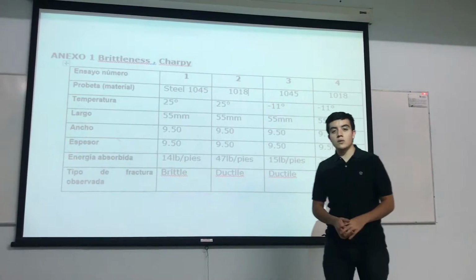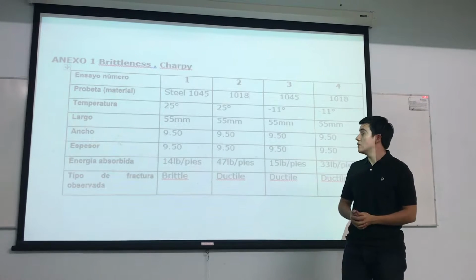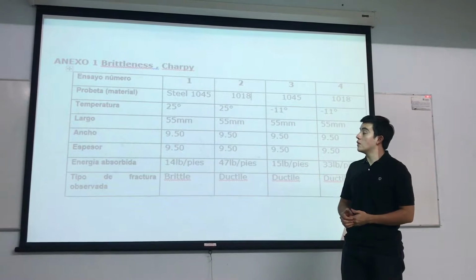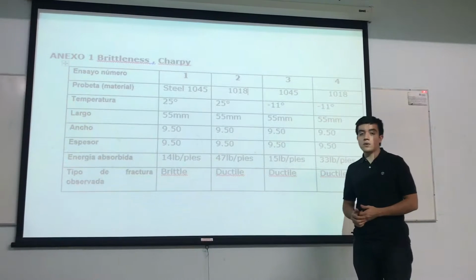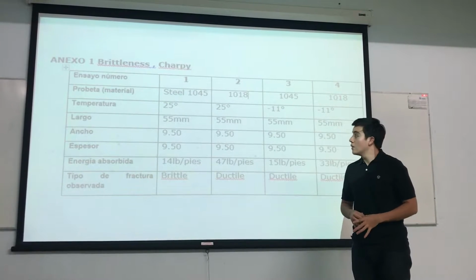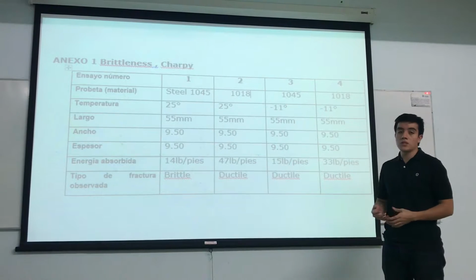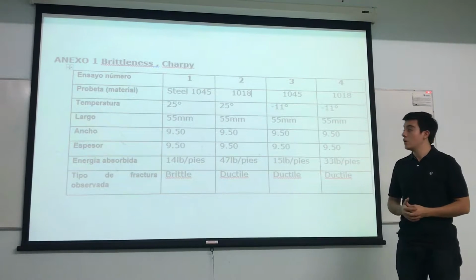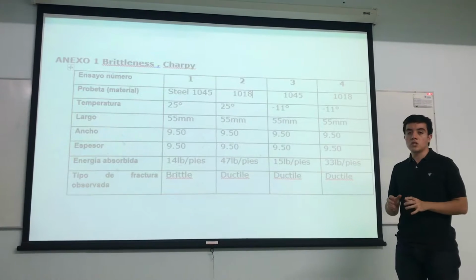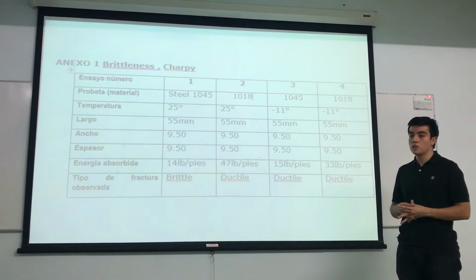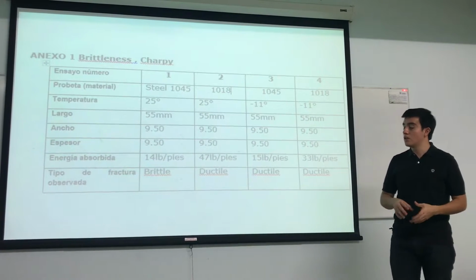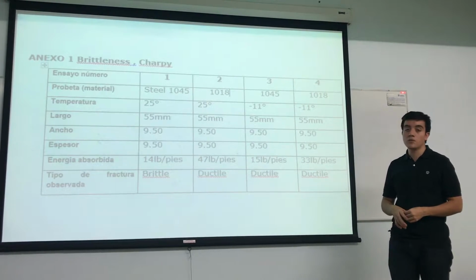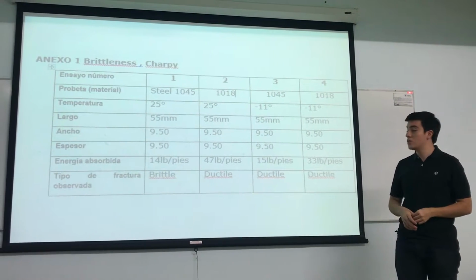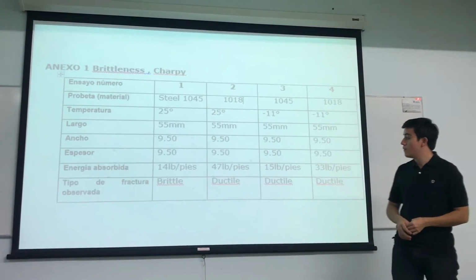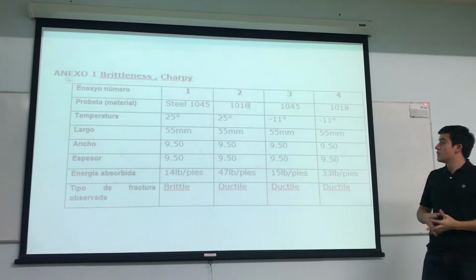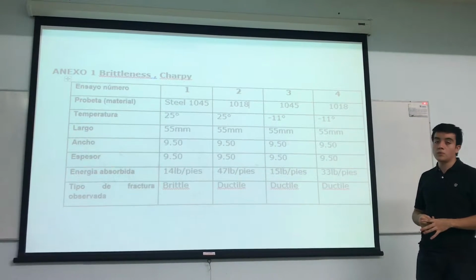Okay, for the result analysis, first, the impact test is a measure of the brittleness of the pieces, and for this practice we use the Charpy method. So for the results we did 4 tests, 2 for the same material and the other 2 the same, but we changed the temperature in both of the 2 tests for the same piece. We can see the absorbed energy in the impact test for the steel 1045 has a result of 14 pounds per feet, and we did the same process for the other 3 materials.